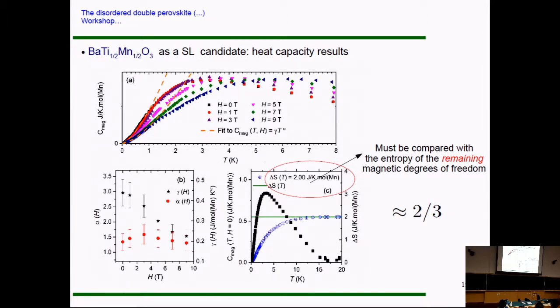And here I will count. That's what I'm doing here. I'm calculating the entropy, and essentially I'm counting how many spins I still have in the system. And I got this number, which you might think is way too small. But I must remember that this number must be compared with the remaining magnetic degrees of freedom, not with all the spins. As I said, I have only a few spins that still contribute to magnetism. The other spins are frozen, essentially. Their entropy was recovered at much higher temperature. And anyway, we still have entropy in the system. We can account for only 2/3 of the entropy.